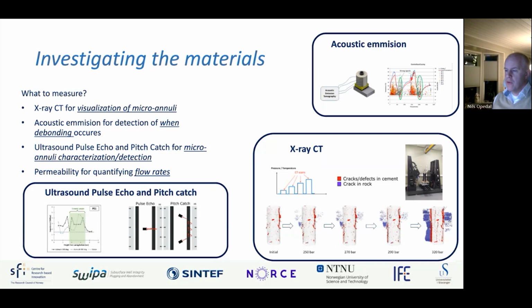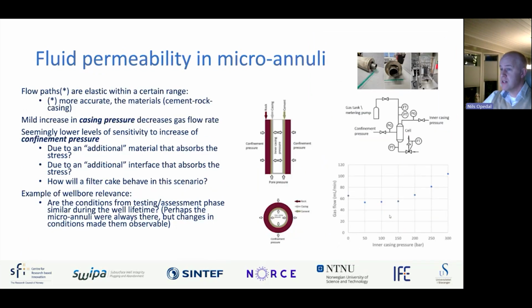For some of the newer tests now, newer cells, we have moved on from acoustic emission and X-ray CT, moved on to using ultrasound pulse echo and pitch catch methods, used more for microannulus characterization and detection. And we also perform flow tests or permeability tests on our specimens to quantify the flow rates or leakage rates, if you like. I don't have any photographs indicating the permeability test because the slide was full, so I can move on to the next slide, showing some highlights, some results of what we have from SWIPA, but also from other projects, our understanding of fluid behavior or fluid permeability in the microannulus for these kinds of specimens.